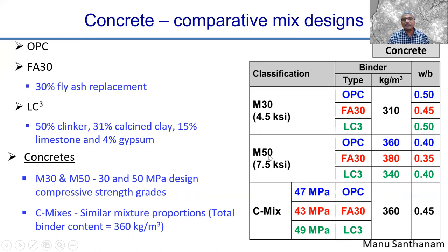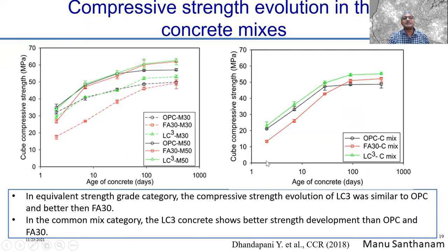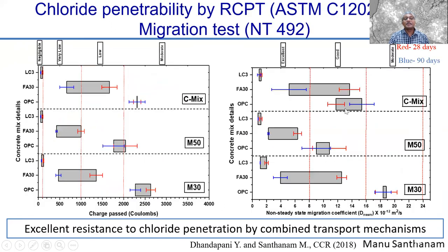So for these M30 and M50 mixes, if you look at the strength evolution or strength development, you don't see too much difference, except that the LC3 systems seem to match with the OPC with respect to early strength, whereas the fly ash based systems, which are in red here, start developing strength very slowly, but ultimately by 1 year, there's not much difference in the different blends. Okay, by 1 year, you really don't see too much difference. The difference is in durability.